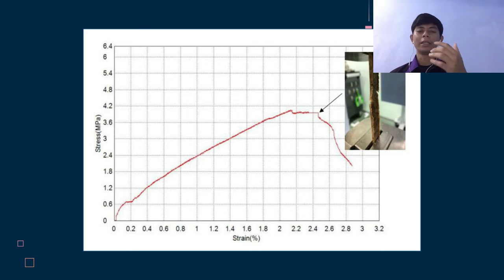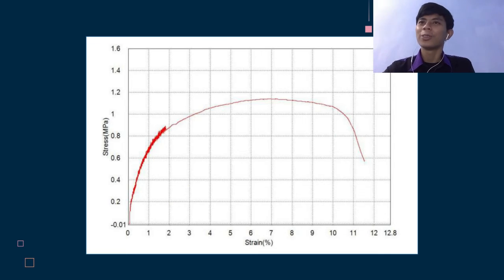This graph represents the lower value of the bagasse, the highest size of the bagasse, the highest PVA and the lower cassava starch. This graph is a little different from the previous graphs, because we can see in the picture that the sample does not break like the earlier ones, it is just stretching. So when it achieves the maximum tensile stress value, it still has a value because the material is not totally breaking up. It is just necking. So we move to the last graph.